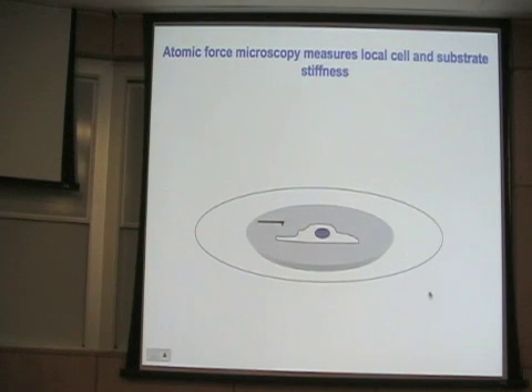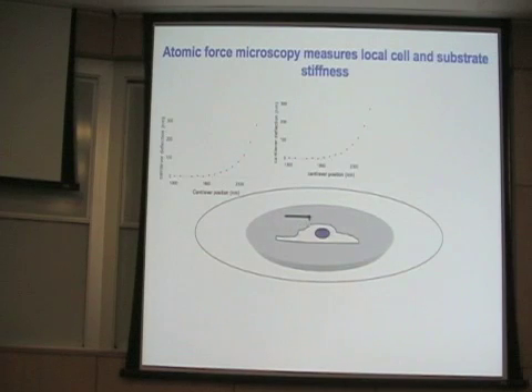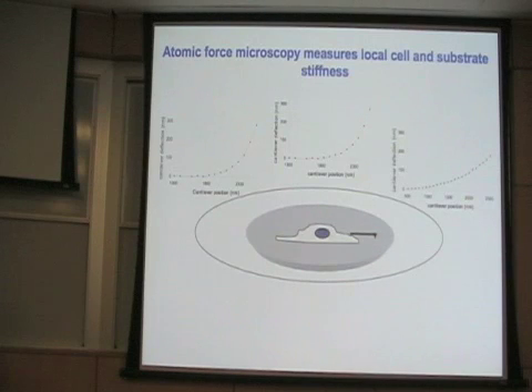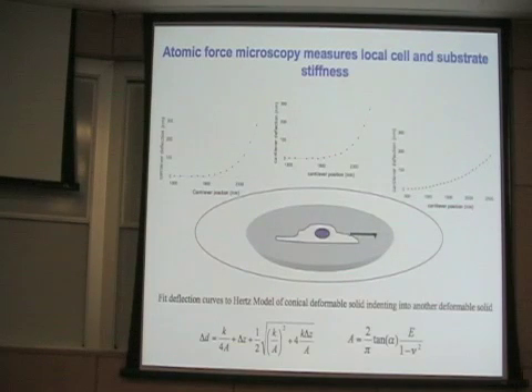Okay, so one of the other things that's come as a bit of a surprise is we've started to do atomic force microscopy with this nice little needle by making a gel, poking on the cell that's sitting on that gel, and then poking on the gel right next to it to get an idea of the relationship between the cell's own stiffness and the stiffness of the material around it. And these measurements, there are technical issues of doing them that there's no sense in going into, but the bottom line is that we can use relatively simple models and get a surprisingly accurate reading of the Young's modulus of these materials, and again about a 1 hertz frequency range and on the order of a 10% strain.